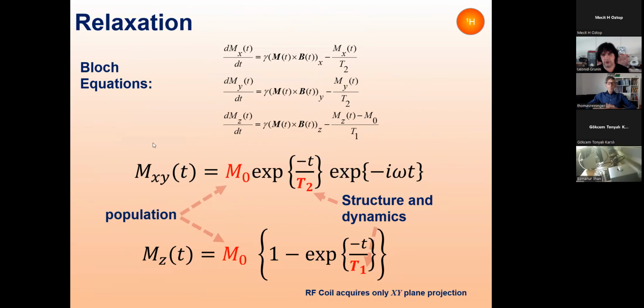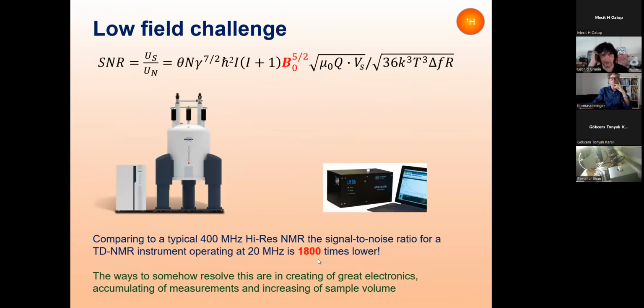Then here, I don't think I need to put lots of attention on this transparency, but look, when you observe the relaxation, the so-called T2 relaxation, you normally see, if it's a simple material, a one-component homogeneous material, the decay. It should be a decay which is characterized by the relaxation time. The amplitude of this decay will be proportional to the amount of hydrogen within a sample. It means the more sample you put, the stronger the amplitude, or it depends on the proton density. And this relaxation time will depend on the dynamics. We will talk about it slightly later. For the longitudinal relaxation, this is a different curve. And here we have the constant parameter, which is called T1, that we already discussed.